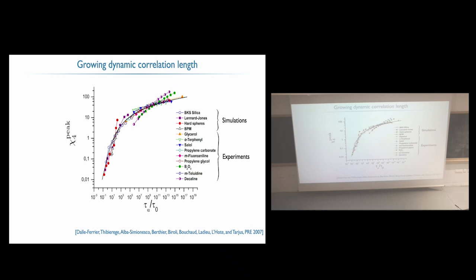And you also see that if this is a proxy for dynamical length, here you have a time scale that's increasing, a length scale that's increasing, but you don't see any divergence in this length scale here. It actually looks like it's saturating. So we don't have something diverging or anything, and the numbers you see are quite small.